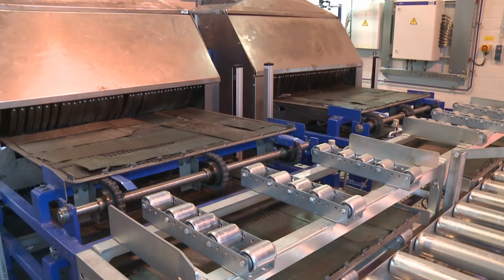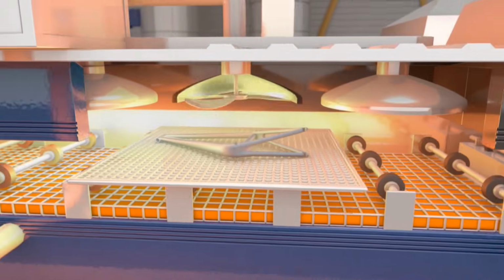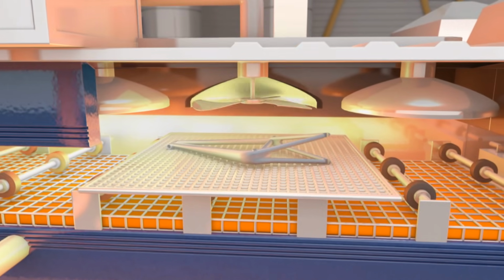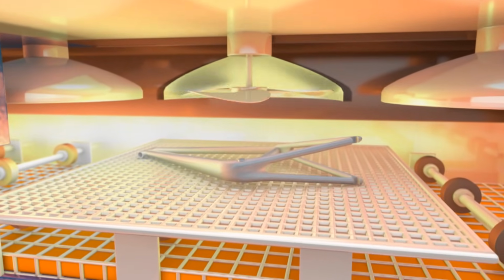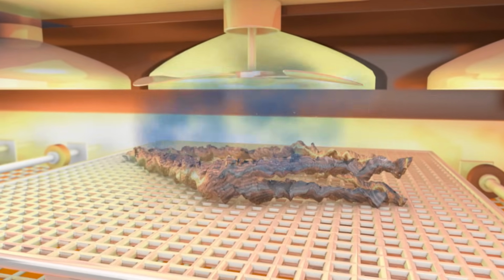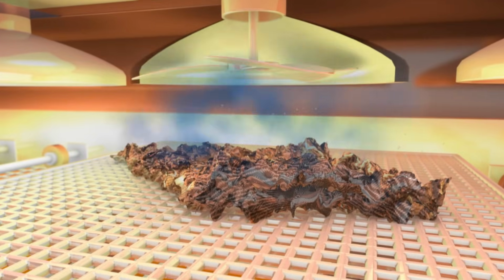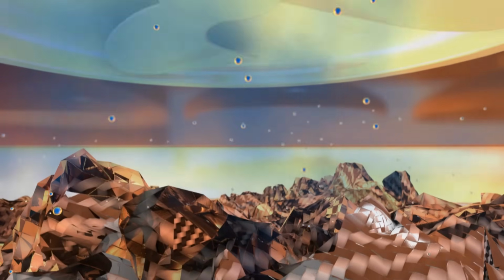During a process called pyrolytic decomposition, the thermochemical division of organic compounds takes place at temperatures of more than 500 degrees Celsius. That means long-chained molecules are broken into smaller ones through heat alone and without oxygen. In the case of the bicycle frame, the carbon fibers held together by long-chained epoxy resin are split apart. High temperatures immediately send the smaller molecules into a gas phase. Only the carbon fibers remain.